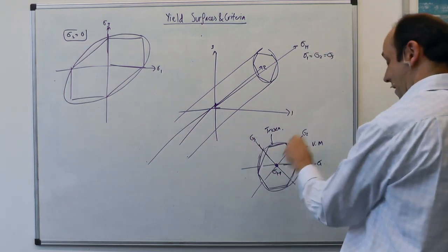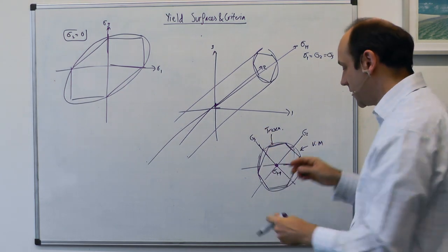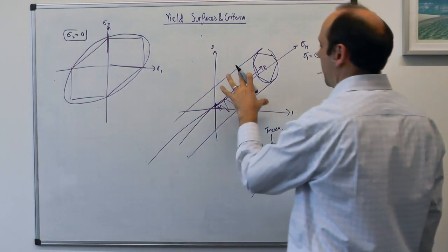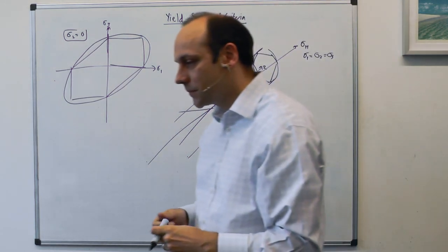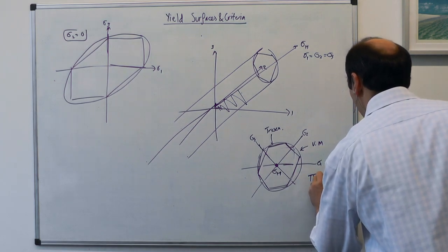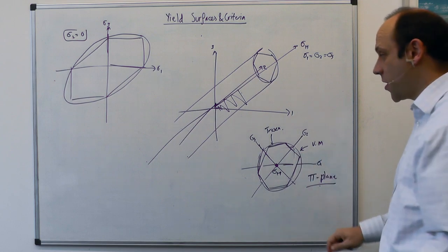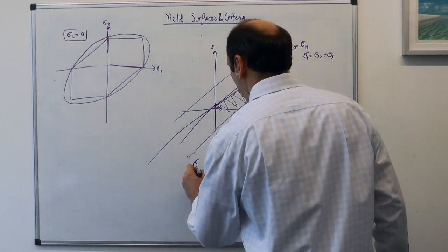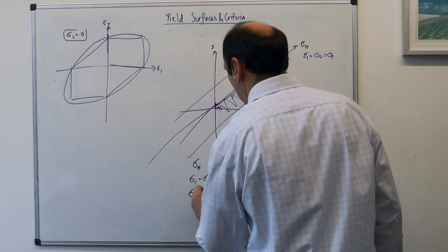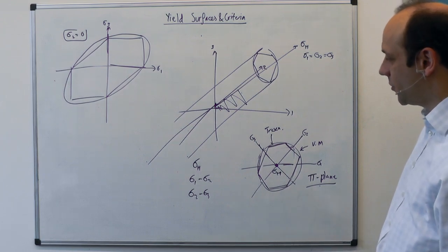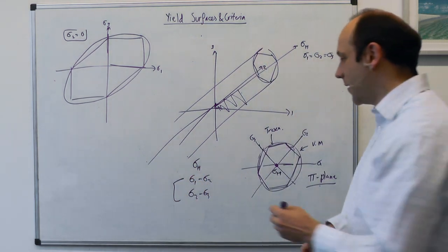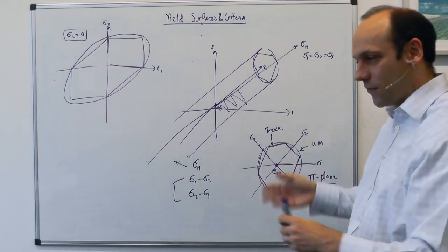And so when you're looking down that hydrostatic stress axis, these two yield criteria suddenly turn from being funny shapes to this regular shape. It's just that we're slicing through, if you like, the basal plane of this cylinder and this hexagonal prism. This is called the pi plane, or the plasticity plane method of projection. So to one view, the way to think about yielding is a hydrostatic stress direction, then one that's sigma 1 minus sigma 2, and one that's sigma 2 minus sigma 3, or something like that. There'll be three independent possibilities for the principal stresses, and one of them we could call sigma h, and then we'd have the other two, and we'd say that yielding only concerned stuff going on in this plane, and this one just caused volume change. And that's the final way to think about yielding.